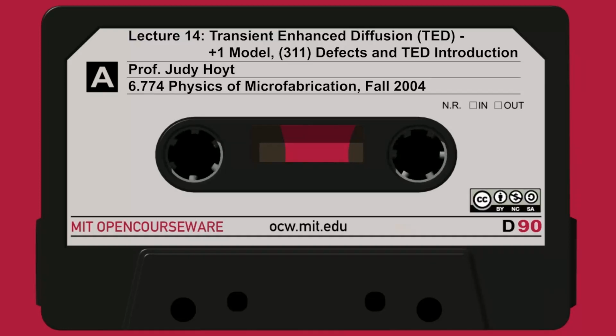And why not? Why didn't people see it? Well, for years, people annealed devices that were very large. They were large in lateral dimension. They were large in vertical dimension. So anneals took place at reasonably high temperature, and they were very long. And so the TED effect, the damage effects, were completely masked by normal diffusion. Because TED, what does that mean? Transient. It only lasts for a little period of time, a short period. So if you put a wafer in a furnace at 1,000 degrees or 800 for 4 or 5 hours, a couple of hours, you're not going to see it.